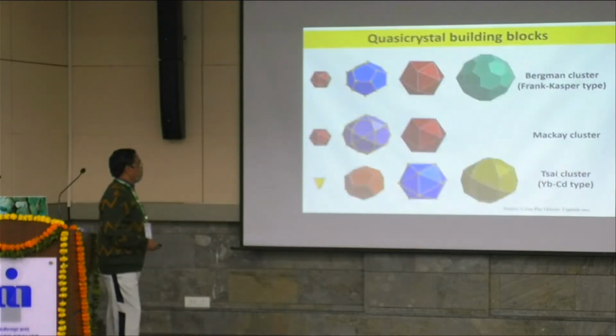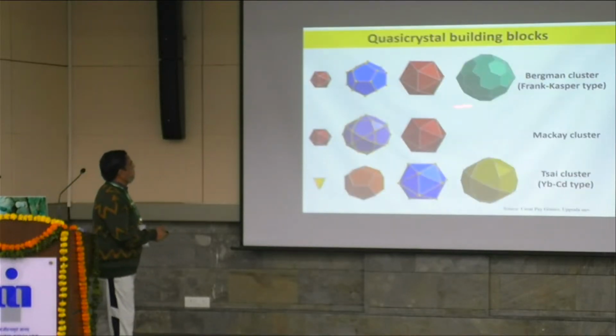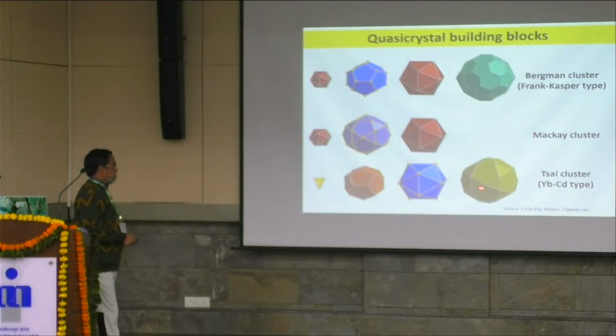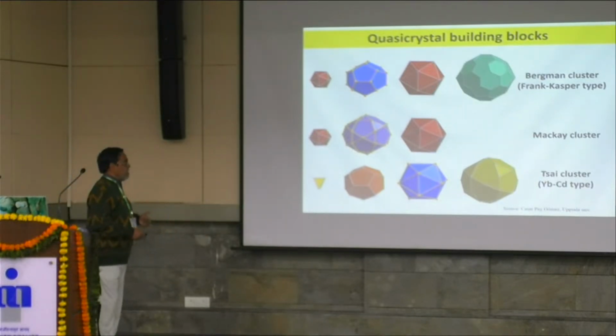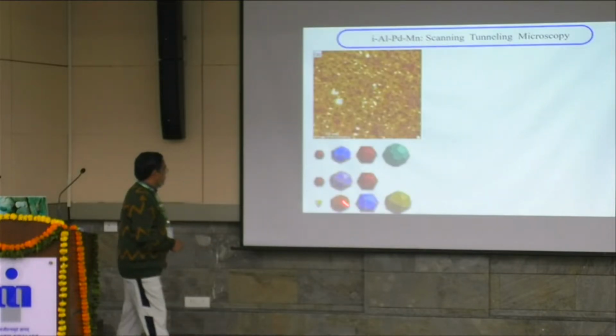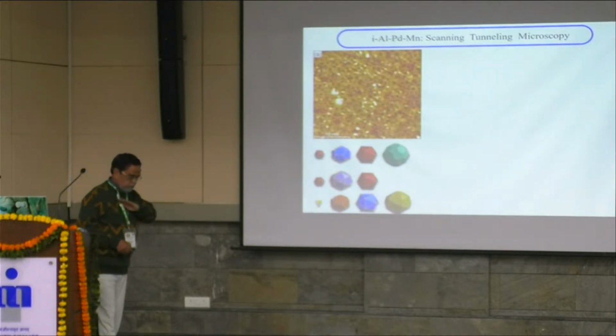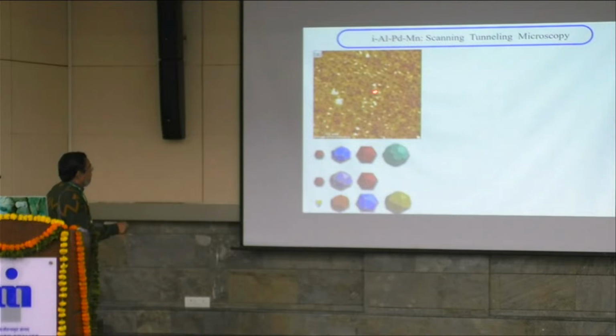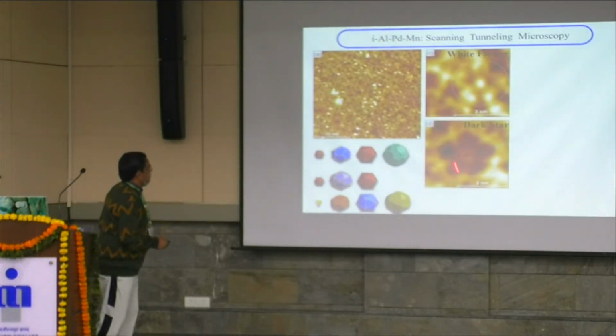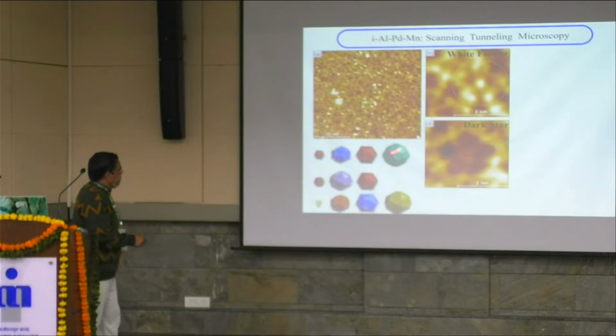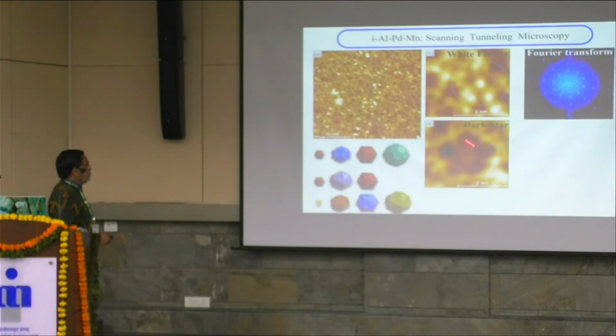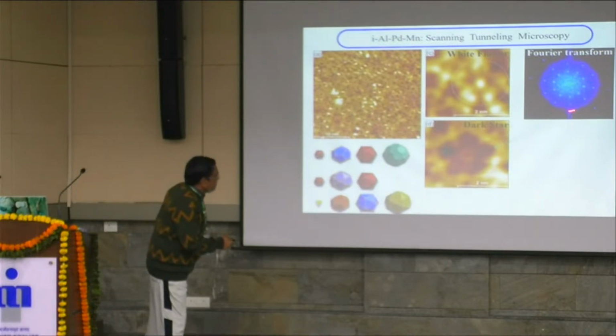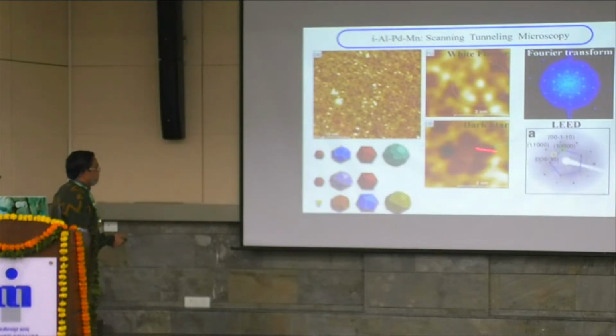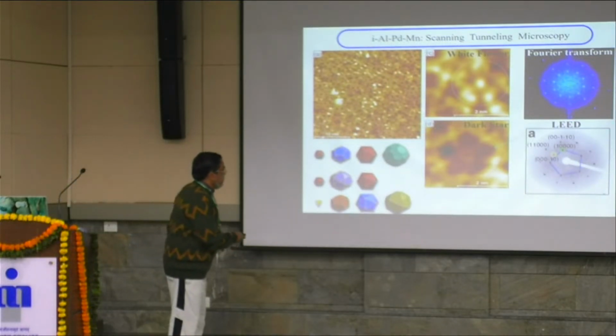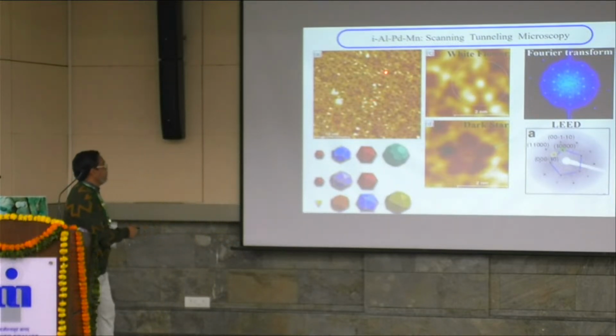They are ternary systems. These quasi-crystals are basically made of different kinds of building blocks called Bergman clusters. They can overlap, and all these are the details of the quasi-crystal bulk structure. I will not go into that, but look into this, that when you cut this, then what the surface looks like. The surface means you are cutting these spheres or semi-spheres, nearly spheres, and you can see that there are beautiful 5-fold patterns. These are called white flowers. This is called dark stars, and these patterns are visible because we are cutting through these Bergman clusters. If we take a Fourier transform, you see nice quasi-periodic spots of 10-fold symmetry here. And if we take a low energy electron diffraction, which studies the surface, we see these 5-fold spots here corresponding to the 5-fold surface.